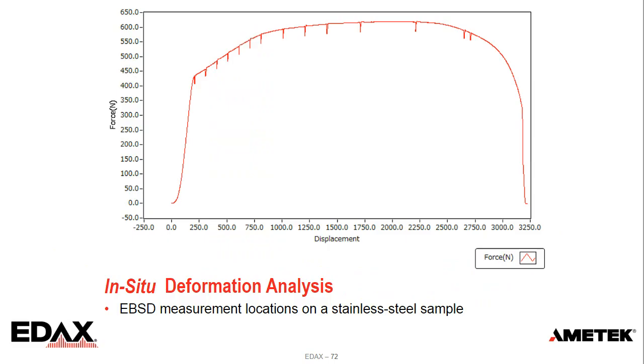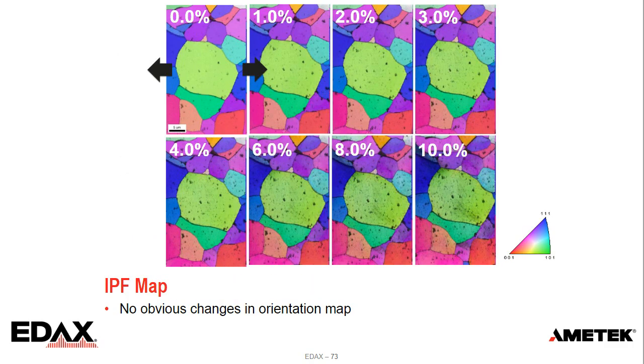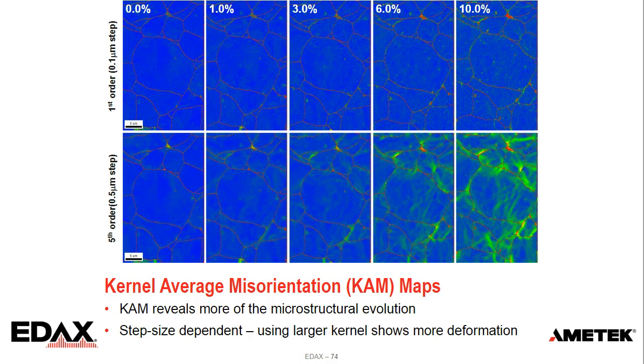We can also do in situ deformation analysis. This is just an example of using a stage where, when we start to yield, the material is our zero point. You can see the little notches where we stop the deformation and measure the microstructure at each point. And we can see, with the amount of deformation, how the microstructure evolves as a function of deformation. If we look at the orientation map, you'd be hard-pressed to say you see a huge change in these particular maps. If we look at it with our KAM, or kernel average misorientation map, we start to see it a little bit. The top line shows our first order kernel. The bottom line shows the fifth order. So we're stepping out further.